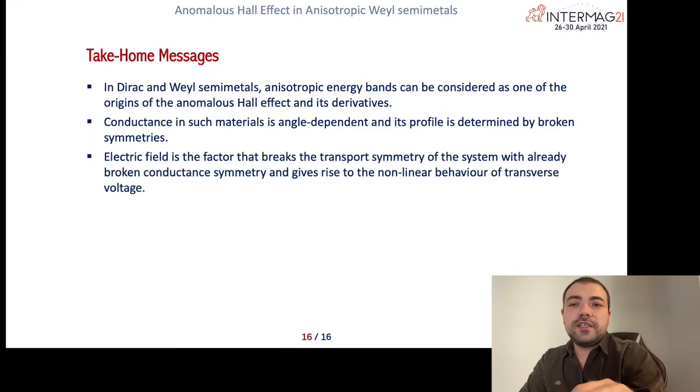Finally, I would like to address the take-home messages. First, in the Weyl semimetals, anisotropic energy bands can be considered as one of the origin of the anomalous Hall effect and its derivatives. Conductance in such materials is angle dependent and its profile is determined by the broken symmetries. Electric field is the factor that breaks the transport symmetry of the system with already broken conductance symmetry and its one of the elements that gives rise to the non-linear behavior of the transverse Hall signal.